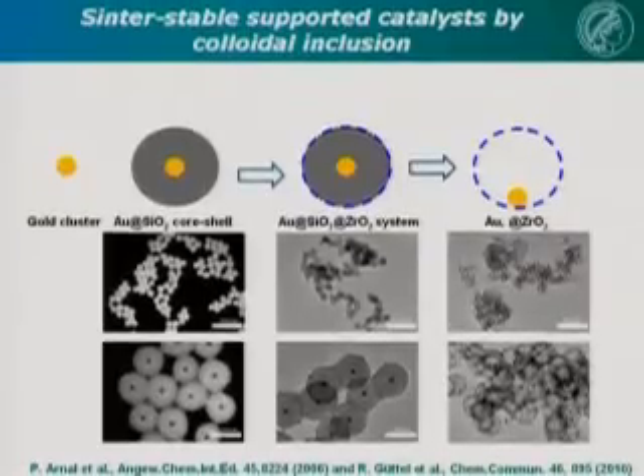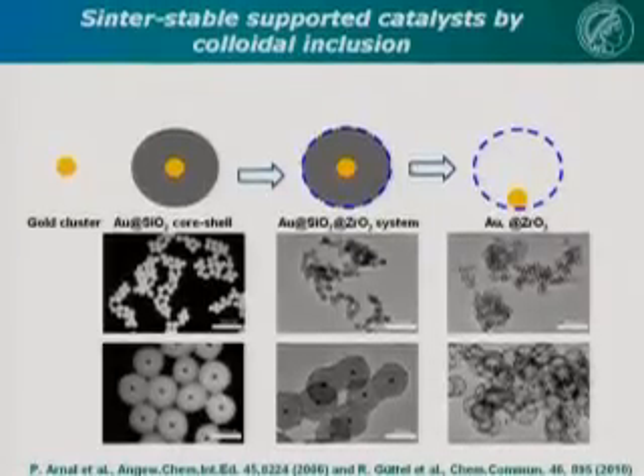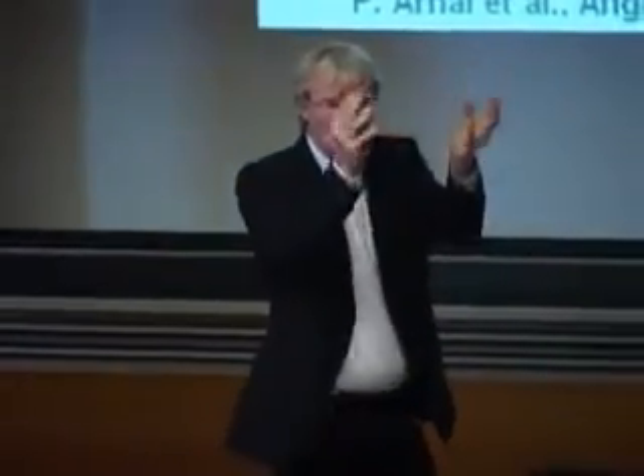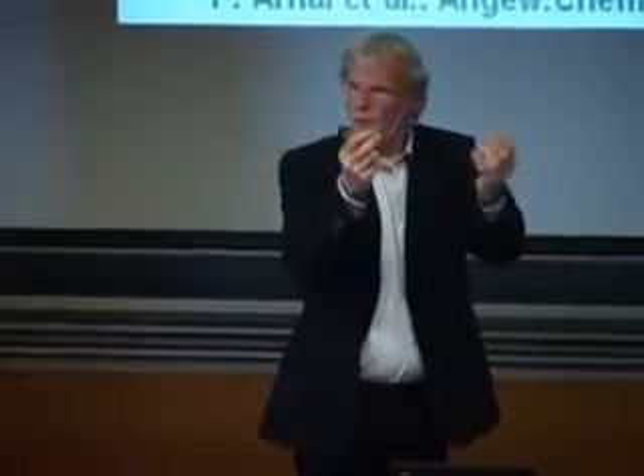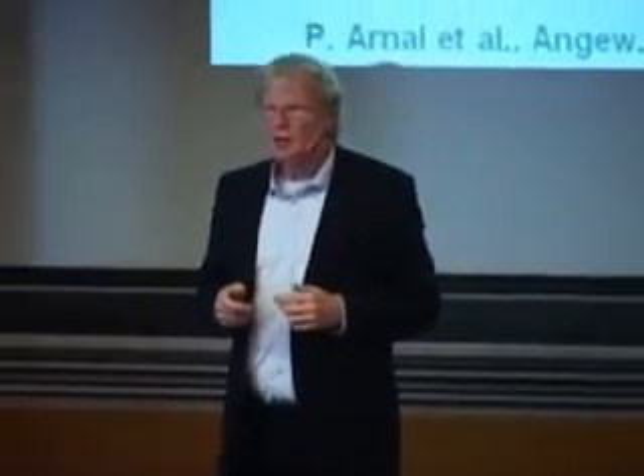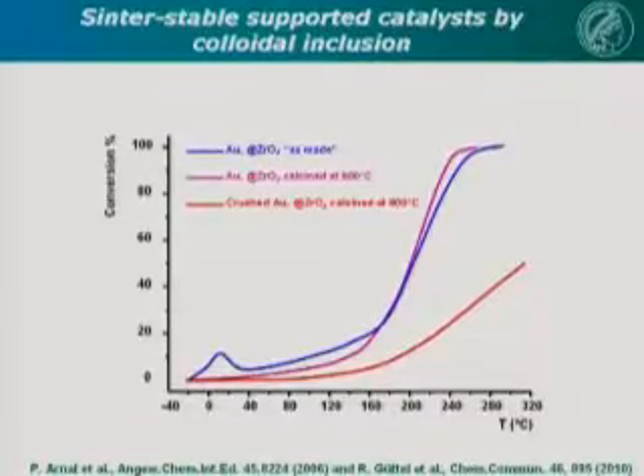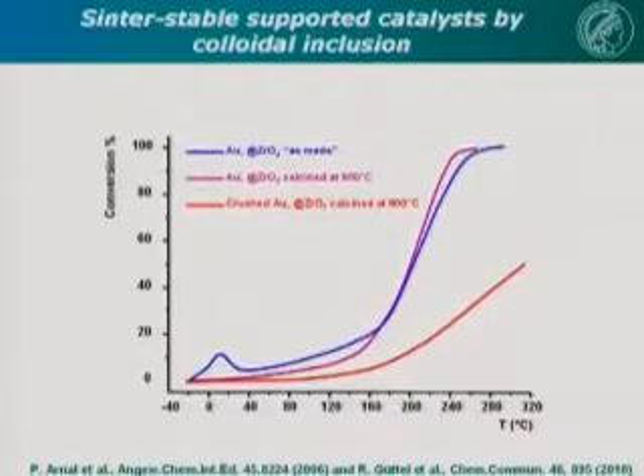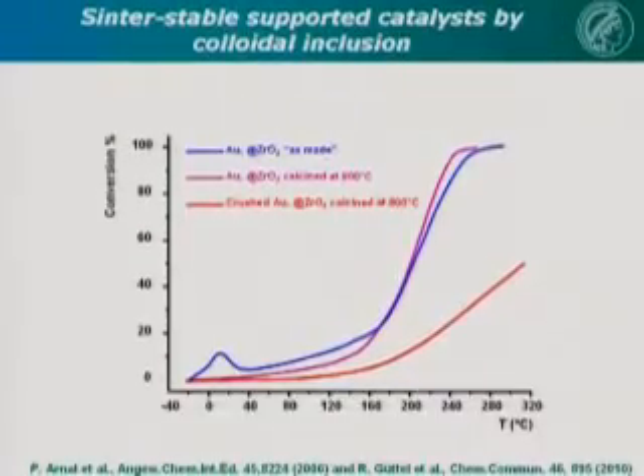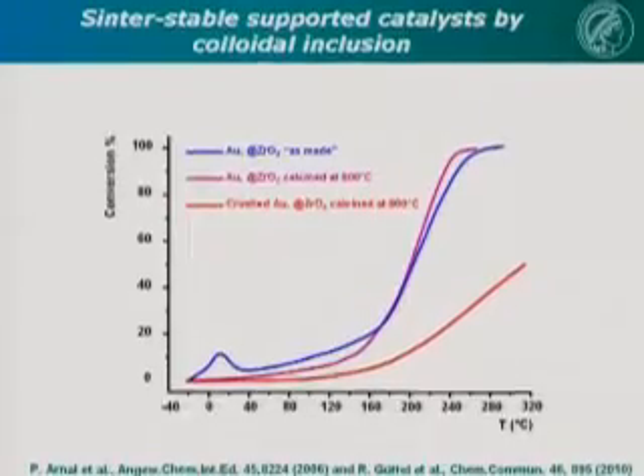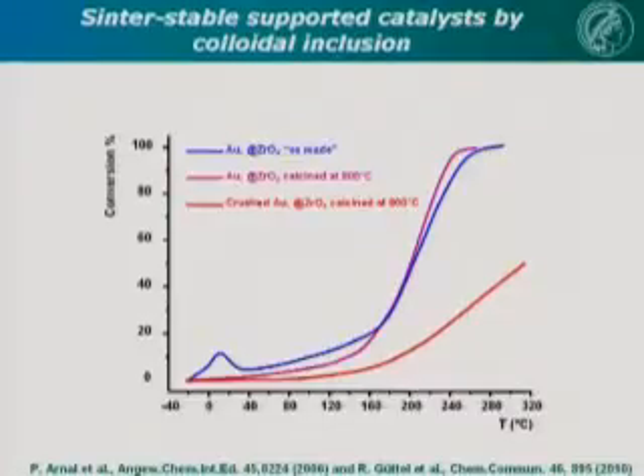And of course, then the gold particles are not in the center anymore because nothing keeps them there. They just fall somewhere onto the inside of the sphere, and this is where they end up. But they cannot leave the hollow shell because the pores are too small for the gold to get out. If we test these catalysts in simple CO oxidation, just as a test, they convert CO relatively nicely for the particle size we have, 50% conversion for the conditions we use at approximately 180 degrees centigrade. These are not the most active gold catalysts.